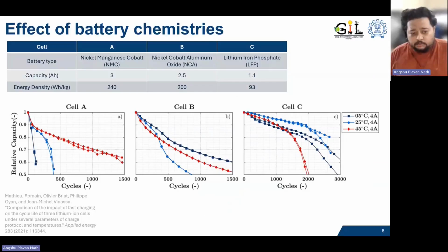The second thing, we also want to show how these battery chemistries affect the degradation of a battery at different temperatures. So if you see here, in cell A, at higher temperature it performs much better compared to lower temperature. At lower temperature, degradation is much faster. Whereas on the other hand, in cell C, the degradation is much faster at higher temperatures, and degradation is much slower for lower temperatures. So which kind of environment you want to use the battery in also dictates which kind of battery chemistry you want to go for.